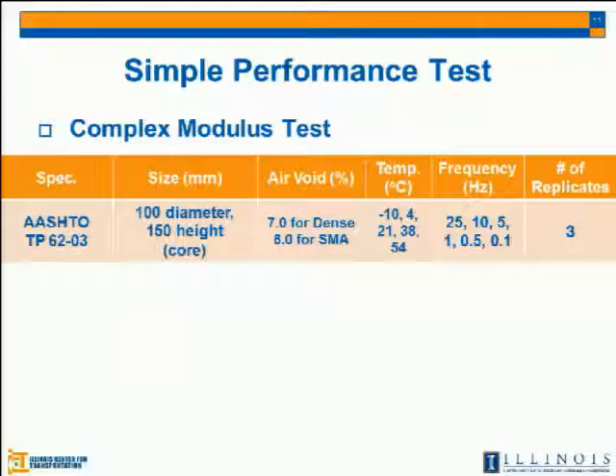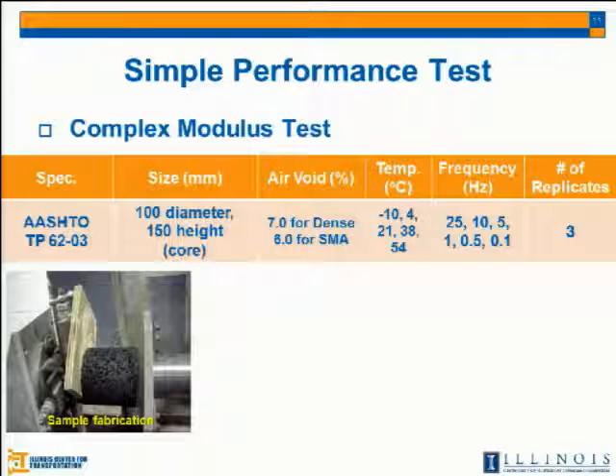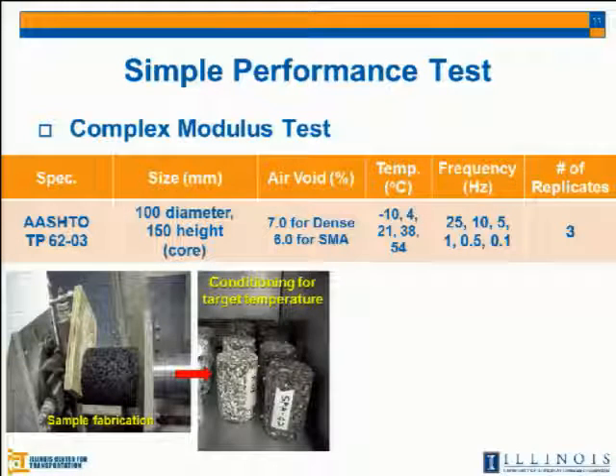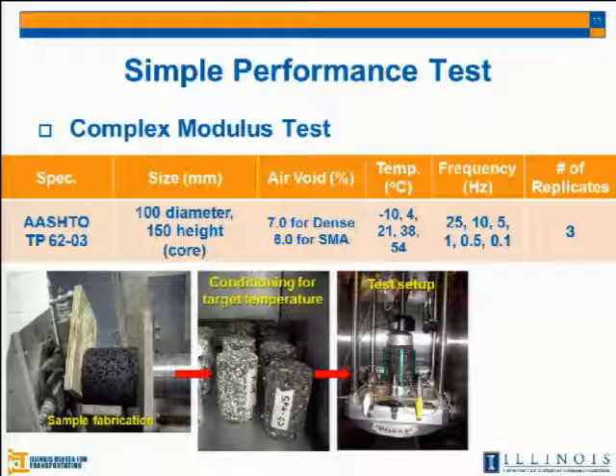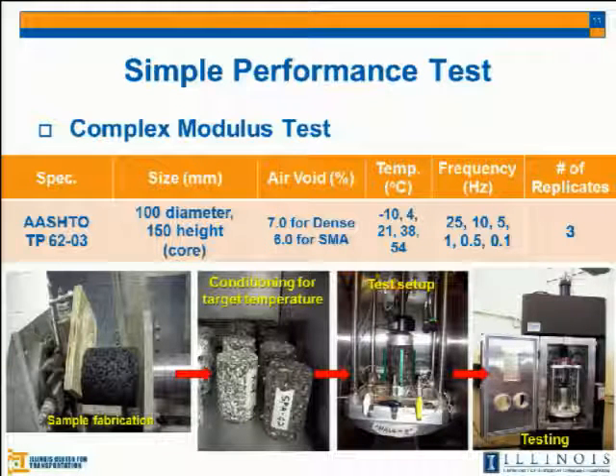Yeah. So first, the lab test is the simple performance test. According to the AASHTO spec, first we make the gyratory sample and then take a core and then did the complex modulus test at 5 different temperatures under 6 different frequencies.